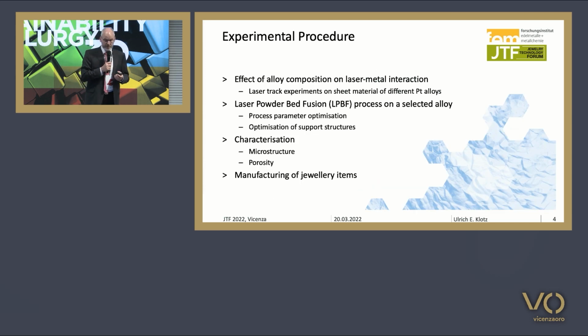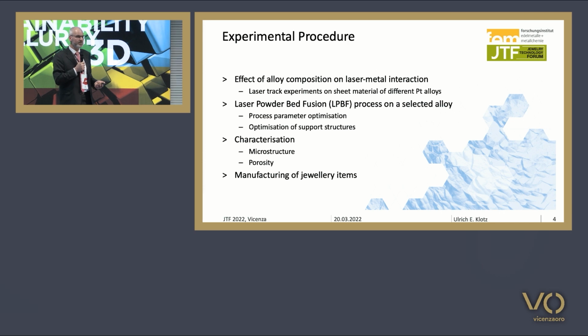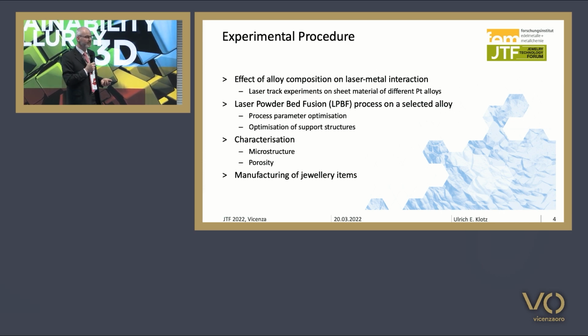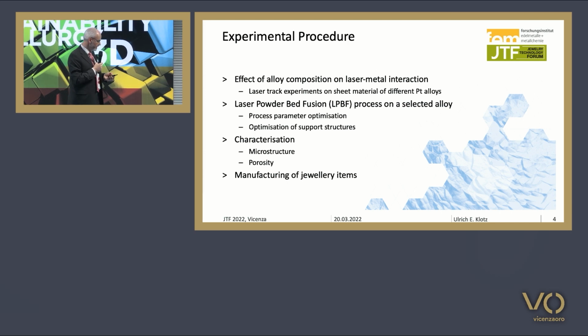So what did we do in our study? We wanted to know about the effect of the alloying composition. To study this, we used sheet material. We prepared small metal sheets that we put into our machine, and we applied laser tracks on these sheets, because this is much easier than producing a powder. Producing a powder means a very large effort—you need a relatively large amount of metal to melt—so we went this way, using laser tracks on sheet material instead.